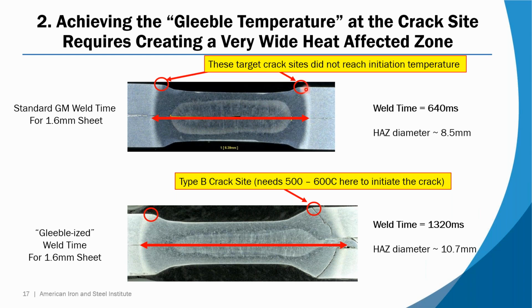We're obviously not up to temperature here. This one didn't crack. We want to warm that up more. The way to do that is with more time. More time allows the heat to go sideways in the weld. More current allows the nugget to go more toward the electrode. So current drives the nugget taller and time drives it sideways.